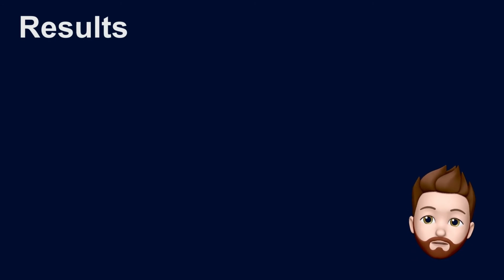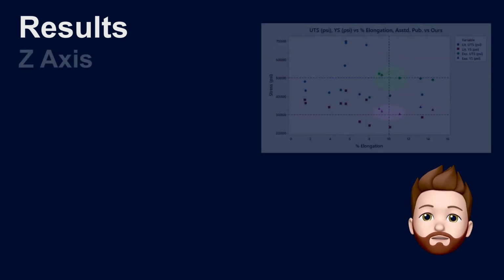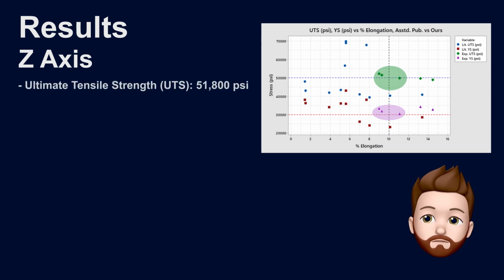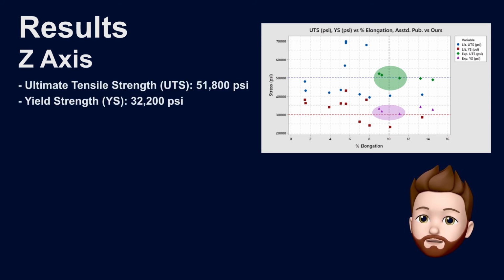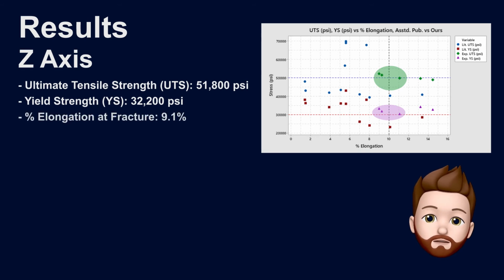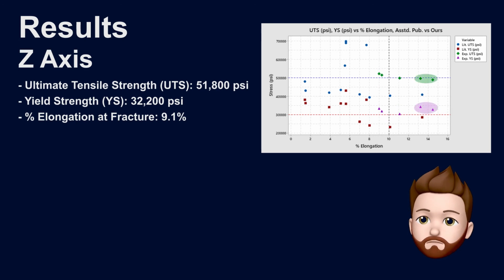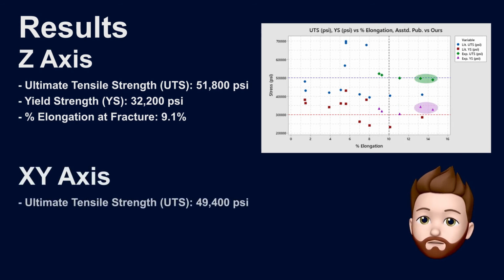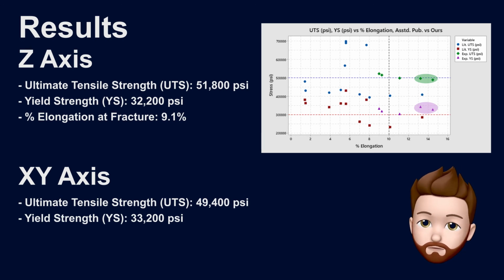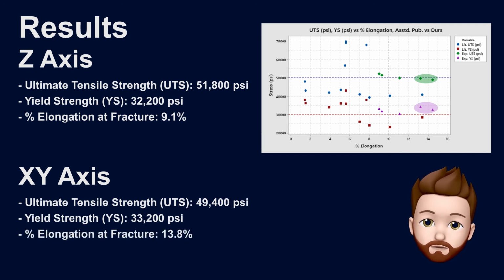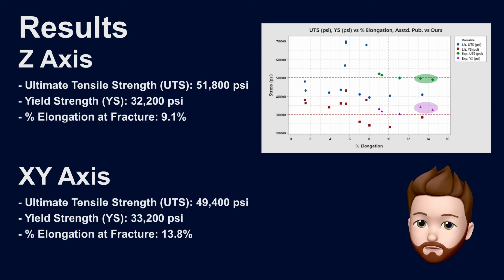Through our experimentation, we were able to determine that 4 minutes at 530 degrees Celsius is the most consistent and ideal temperature for heat treating this material. This resulted in a mean UTS of approximately 51,800 psi, a yield strength of 32,200 psi, and a percent elongation at fracture of 9.1% for the Z-print orientation. For the XY axis, these values were 49,400 psi, 33,200 psi, and 13.8% respectively. All of these values are at or very near the desired results provided by Lockheed Martin and show significant promise when compared to other published results.